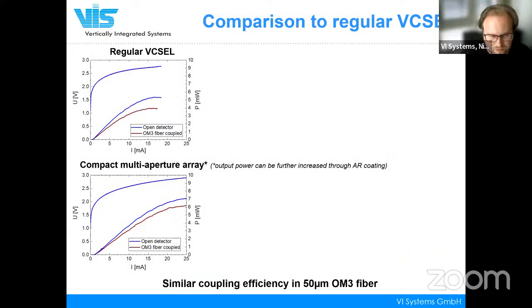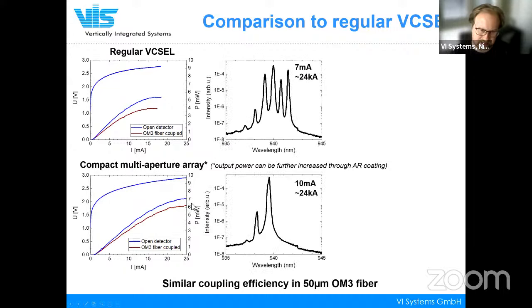So when we compare these two VCSELs, we see that the thermal rollover in mini array is further away. The output power is very similar. The threshold is a little bit higher because we have 4 emitters, not 1. But the 80% fiber coupling to OM3 fiber can be easily realized. But the main benefit, and in this sense, these chips are very similar, but in their spectral width, they are very different. You see that the multi-aperture array has nearly a single mode spectra, approximately 0.1 in RMS.